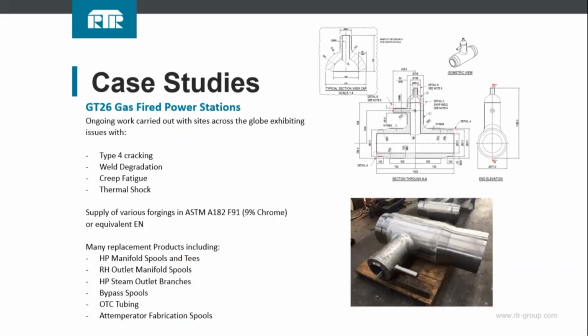And as things develop, we're seeing an awful lot of work in GT26 turbines, particularly in the UK, where there's been a lot of issues with type 4 cracking, weld degradation, creep fatigue and thermal shock. So we've done an awful lot of work in 9% chrome, supplying, for example, this integral forged T for manifold spools, reheat outlet manifolds, done an awful lot of bypass work, OTC tubing and attemperator fabrications. And we would encourage anyone with similar setups and the GT26s to come forward and have a chat with RTR, as we may have been producing products that meet your requirements.